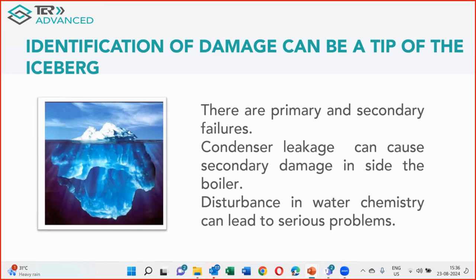because micron levels of leakages can be identified with them. And minor additions of water won't even be caught in the conductivity measurements people do of the condensate. So whenever there are problems, it gives you indications where the problem will occur, and those need to be considered during remaining life assessment.